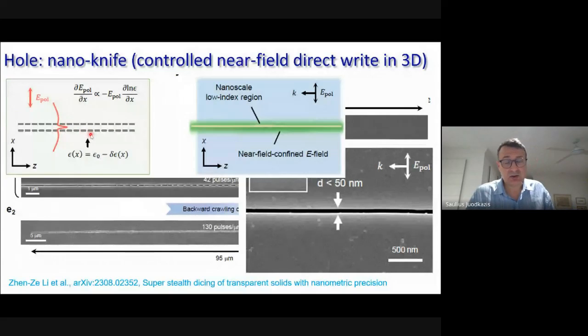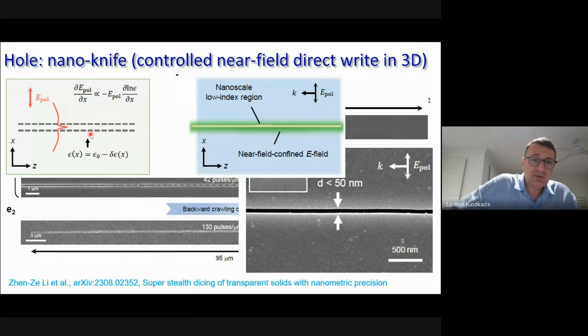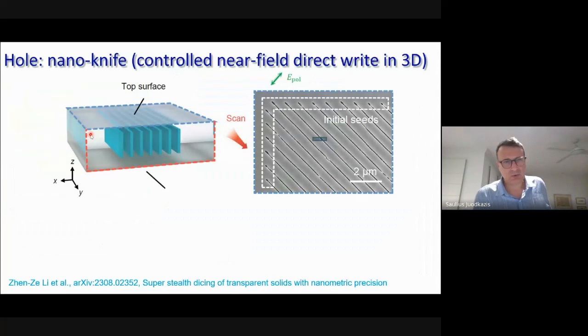That light is not propagating, it's not a waveguide, because this is low refractive index, but it's because of that interface, localization of light near field is enhanced. So we can modify subsurface. Surface is not ablated. We are modifying with a Bessel-like beam inside the glass volume. Then it was polished to reach the modification area, and etching out in wet etching conditions was used to reveal the structure. And have a look.